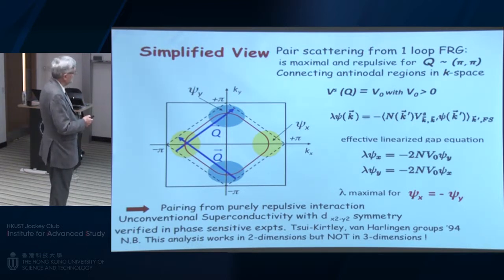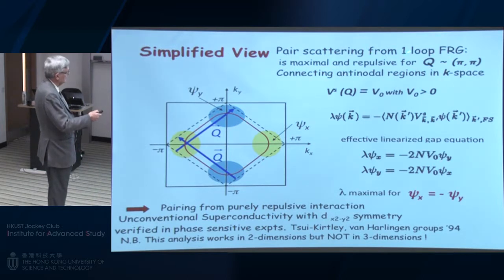And this is a simplified view of how this works out so well in the cuprates, because the pair scattering that I showed you here, if we start with a Hubbard model, is essentially a delta function, essentially constant in Q space. But if you calculate the effect of the Coulomb interaction in functional RG, just in the lowest one loop, you find it develops structure in Q space, and it peaks up at pi pi. But pi pi is exactly connecting these points of the high density of states that I mentioned.